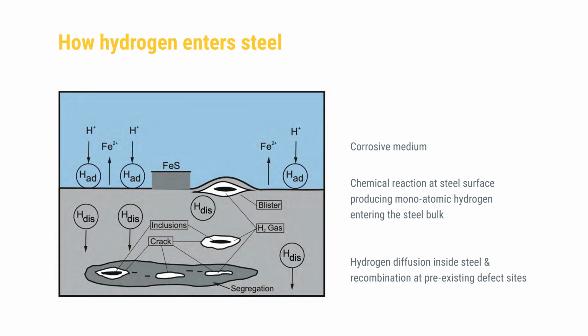Hydrogen as a single atom is very mobile in the steel lattice. So that means hydrogen, once it gets into the steel at the surface, diffuses then in the solid steel to certain places where it can accumulate. This aggregation of hydrogen is not really big. We are talking here about ppms of hydrogen, parts per million of hydrogen, but it can cause, by localized accumulation, significant damage. It alters certain fundamental material characteristics, and leads to localized embrittlement or localized increased plasticity. And these features trigger secondary problems that lead to macroscopic damage.